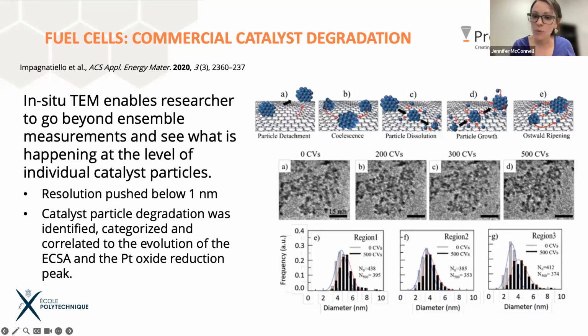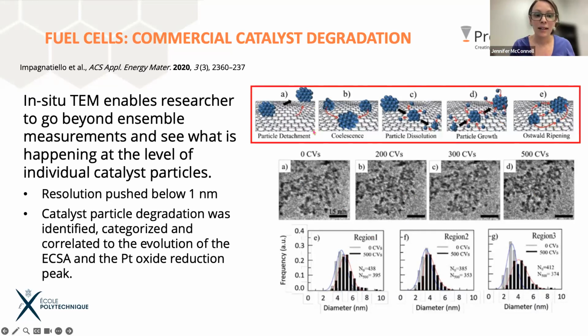And they're just trying to understand which pathways were taken as they undergo the aging, the electrocatalytic aging. And so they ran up to 500 CV cycles to really replicate the stress of a fuel cell, and then did measurements on the sizes of the particles and how they changed over time from 0 CVs up to 500 CVs.